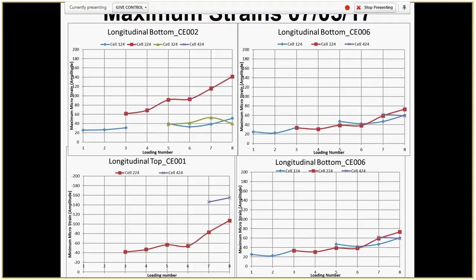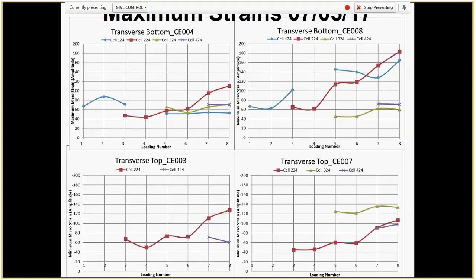It's interesting that cell 224 shows the highest tensile strains at the bottom, but these trends are more or less consistent. But again, this cell didn't have any visible damage, and as we see later, even if there was a macro damage, it kind of self-healed. So in this case, the longitudinal strains and transverse strains have the same trend. 224 shows the highest increase, but definitely no damage. Here I would like to point out that the measurements were taken before saw cutting, so the behavior is slightly different than after joints are formed.